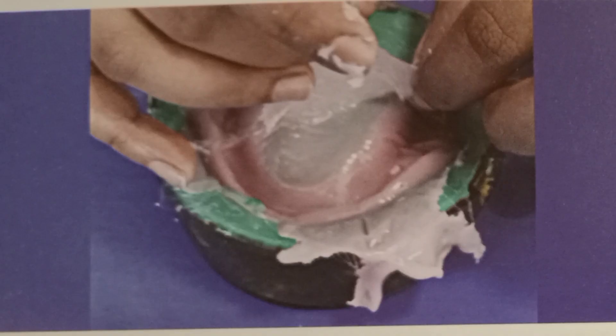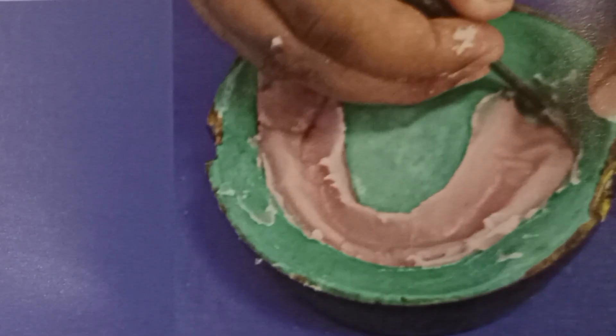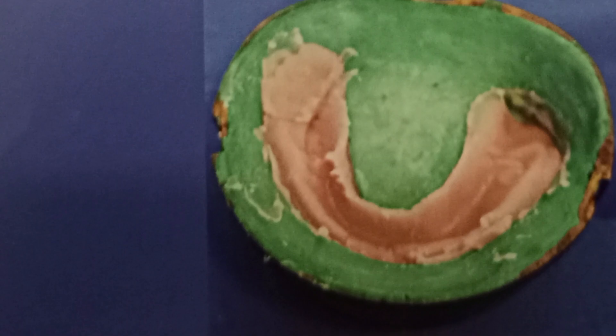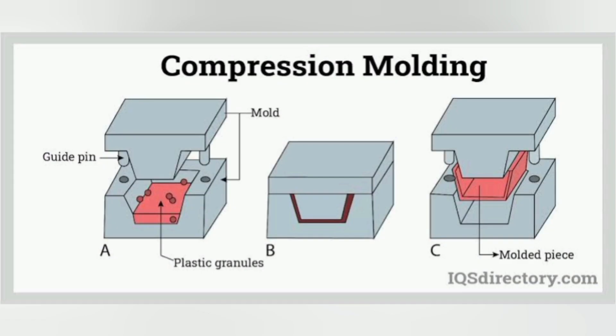The final bench press is at 3500 psi — both pressure values should be remembered. After the final bench press, all extra flash is completely removed. Then the cellophane sheet is separated, excess material is trimmed from the cast, and the remaining acrylic flash is removed.